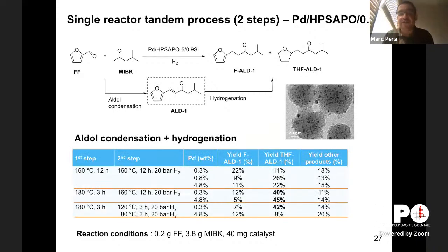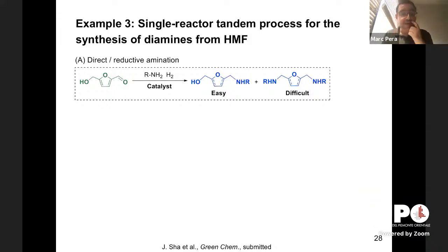Here are some results on the single reactor process. So we optimize the first step and the second step all in one pot. The maximum yield toward this product is 45%, out of more or less 50% of all products. We have yield to other products that come from the other aldol condensation products that I showed before. So the proof of concept is there. We can design a single reactor process by combining aldol condensation and hydrogenation. That's very briefly, because I think that I don't have much time.